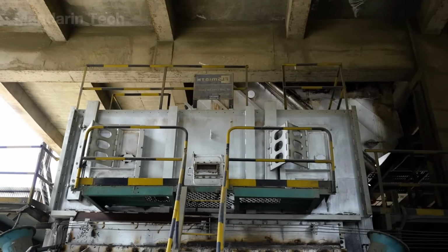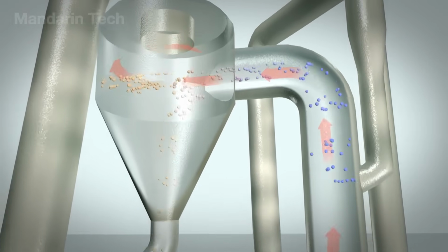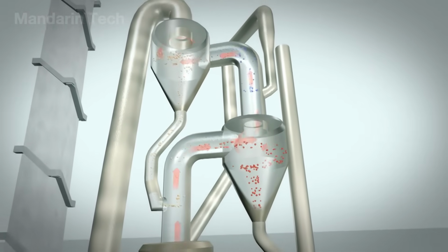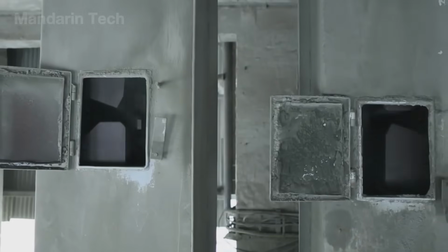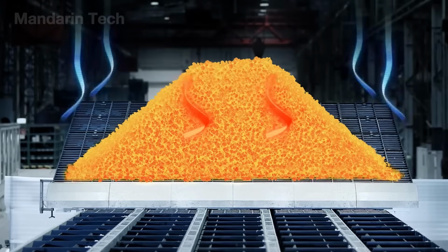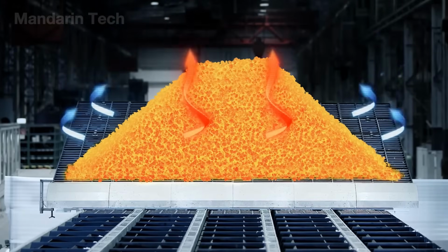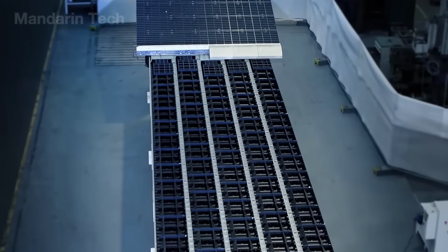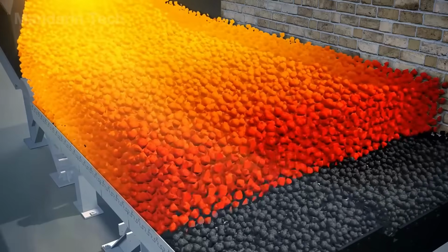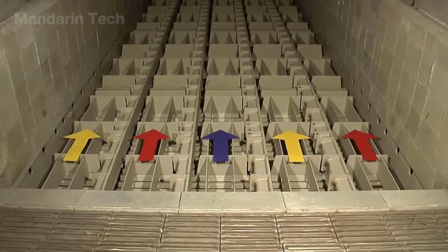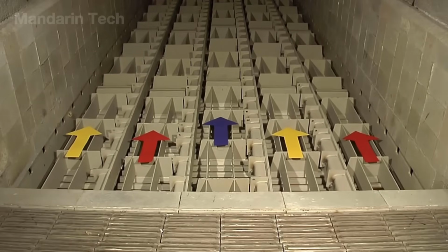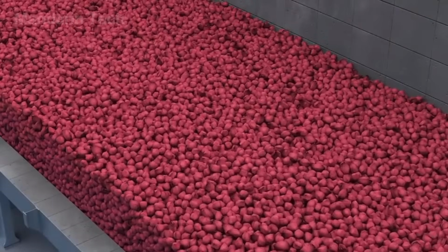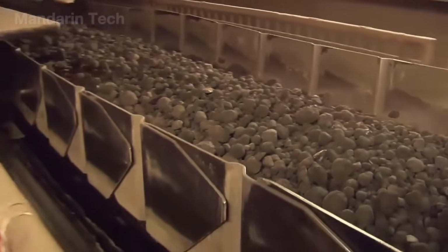The red-hot glow still clings to each clinker as they slide out of the rotary kiln, their constant movement carrying them straight into the cooling system. On the moving grate, powerful blasts of cold air are pushed upward from below, taming the intense heat that's still well over 1,000 degrees. Each clinker slowly changes color as it cools, sending waves of heat rising in steady pulses. The haze of warm air mixes with the fading red light, creating a vivid scene where heat and mechanical motion blend together in the process of stabilizing the clinker's mineral structure.